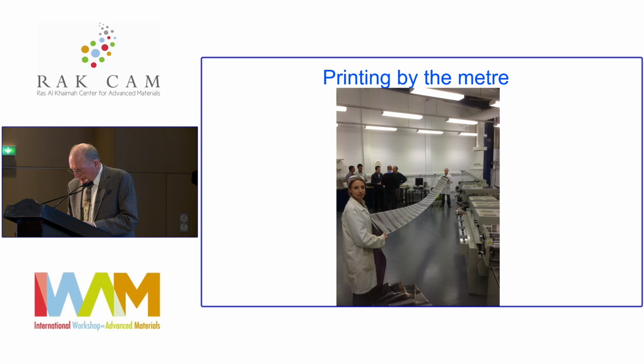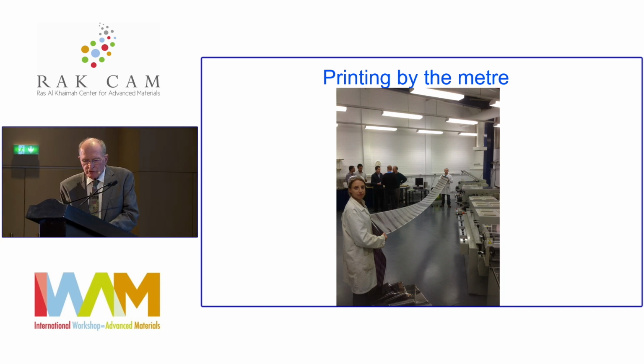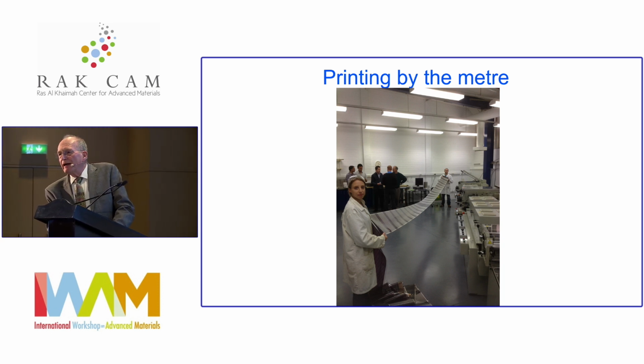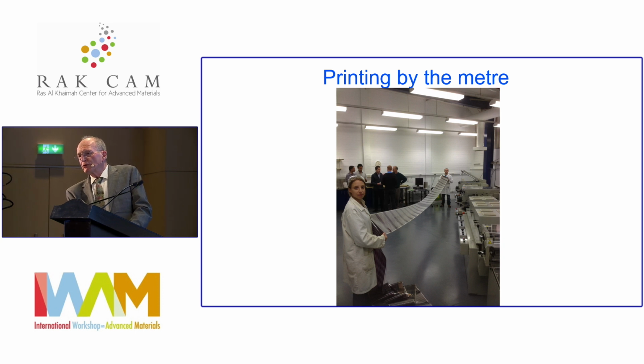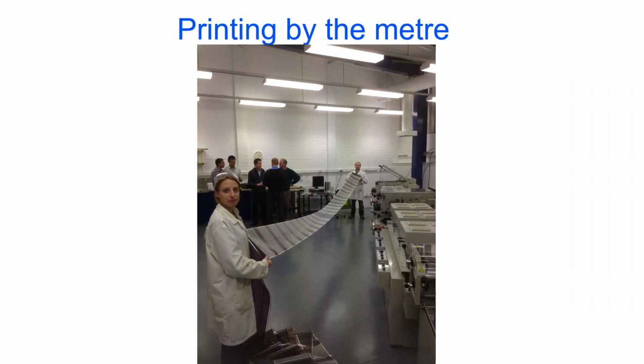Well, in our Victorian consortium, we had set ourselves also being able to prepare A4-sized sheets of printed solar cells. We were still using fairly simple combinations of donor and acceptor materials based on the polythiophene and the fullerene, because this was really a proof of principle that one could do large area deposition. And this is the size of our screen printer, which put the top silver grid electrodes onto the device, which was all deposited by what I'll call roll-to-roll printing, but it's a deposition technique.